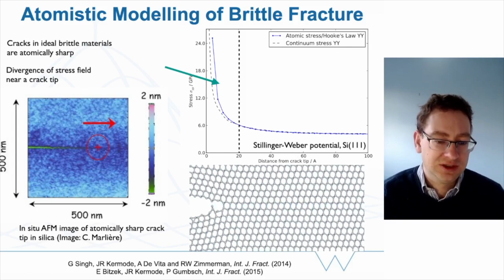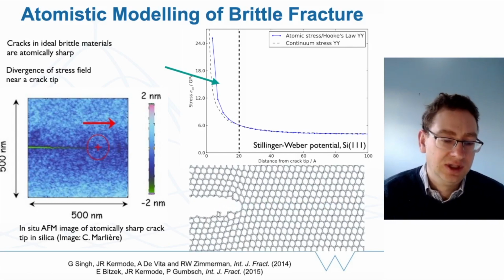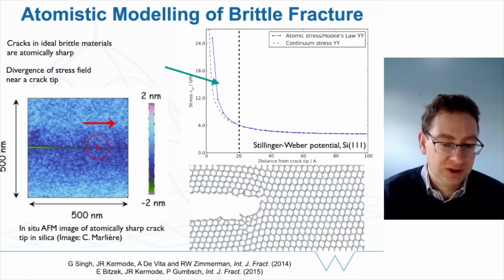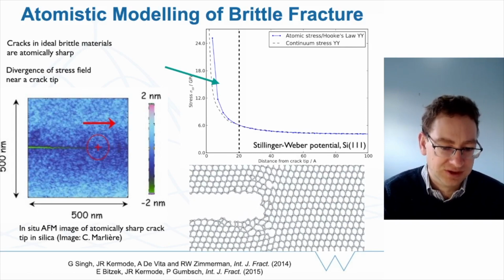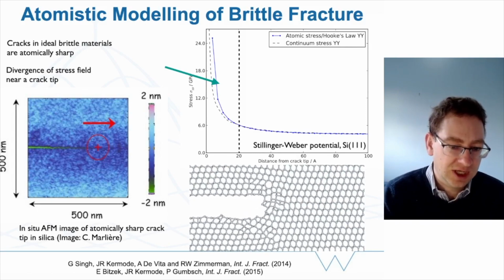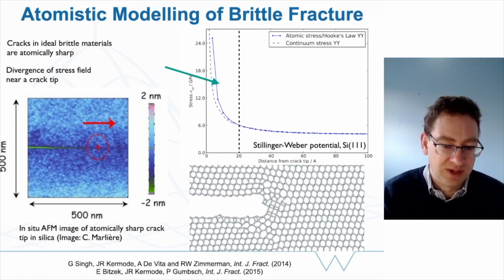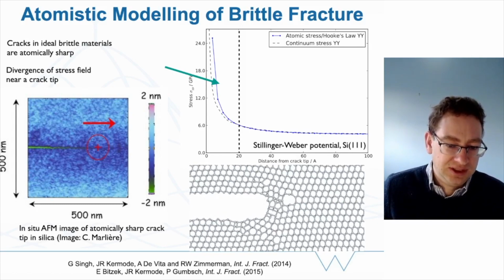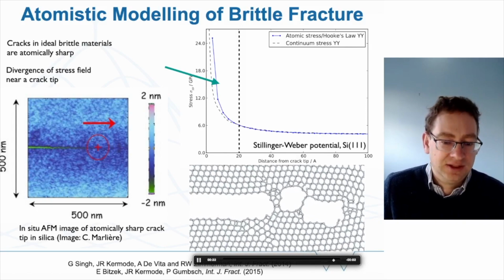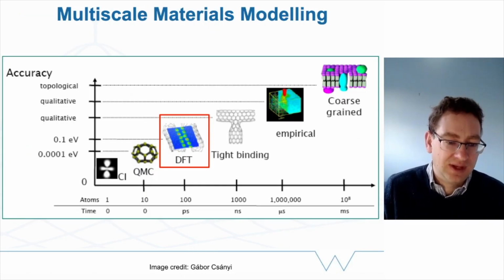But if we run a simulation just using one of these simple interatomic ball and stick models, we don't get a very good description. We see that instead of being completely sharp, this crack gets a bit blunt and gets messy. We see all of these nasty triangles and other shapes of atoms around here that we'd prefer not to see. This isn't a good model of what's going on in reality. And in that case, we have to go up to another level of accuracy.